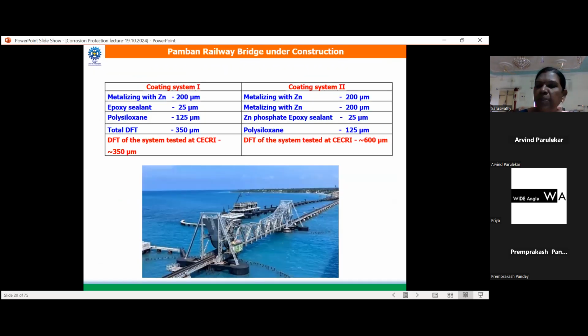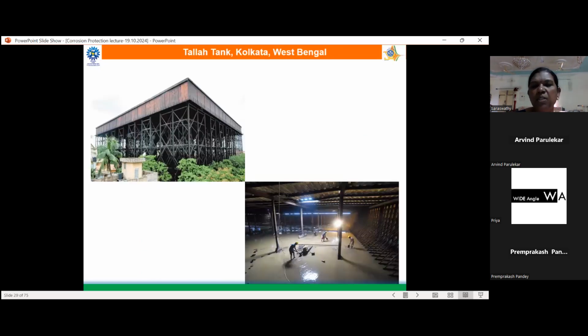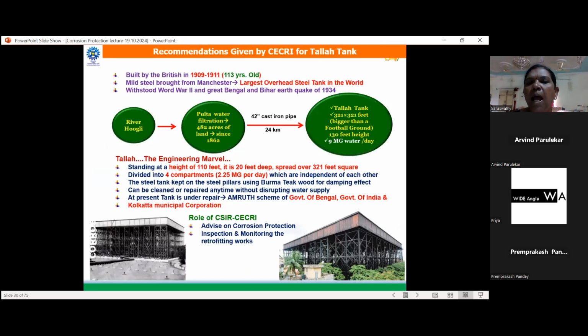This is the system which we have recently tested. This 100-year-old bridge in Rameswaram, a railway bridge, is under reconstruction. For the first time in India, they have used stainless steel rebars for the construction of concrete piers and pillars, and they have used metallizing zinc and epoxy, these two types of coating, for the entire bridge, including the lift span. We have tested this coating at CECRI, and we found that the system performs well in this harsh marine environment.